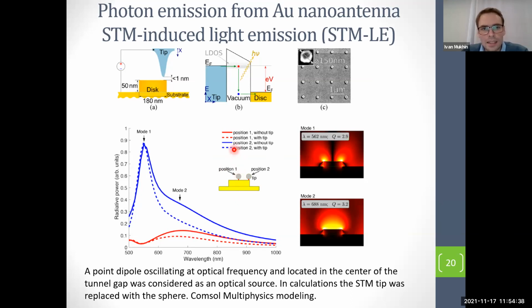In the center, this is position number one. This is the red curve. You can see that we can excite a plasmon mode of an antenna, which is shown here, and the wavelength is about 690 nanometers. But if we move the tip to the periphery of the nanodisk, this blue curve, we can see that we excite the same mode, and also we have another mode close to 560 nanometers.